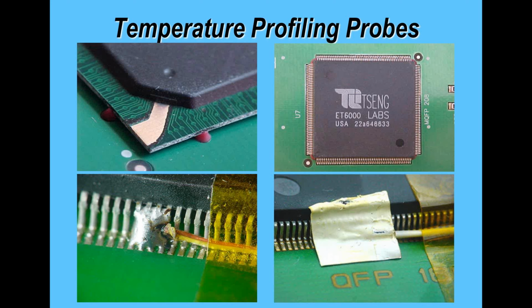That weight is not important, it's the number of solder terminations in contact. On the top right hand side of this slide I show again a QFP. This is a ceramic QFP package, and I've put adhesive on the four corners as well. The reason being that it's quite heavy, it would fall off. So you're only doing this to help your profiling and also making sure your boards are always representative.